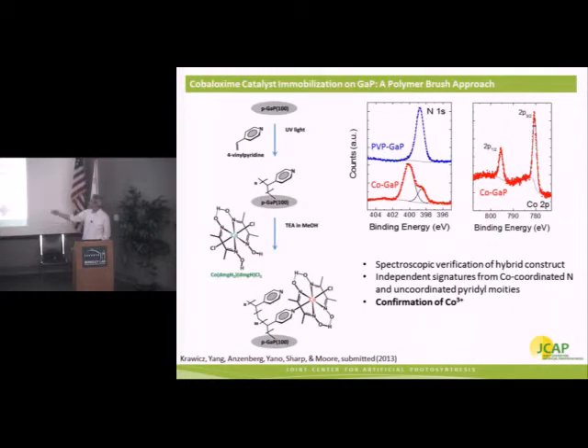In a real system, here we don't want to just use polystyrene like I showed on the previous slide. Here we use vinyl pyridine as our monomer. We immerse our activated substrate into that, illuminate the substrate, and this leads to the growth of a polymer brush layer on the surface. These pyridyl units can then be reacted with a cobalt catalyst in this case.